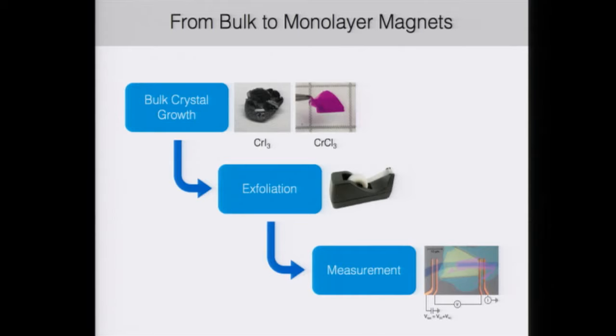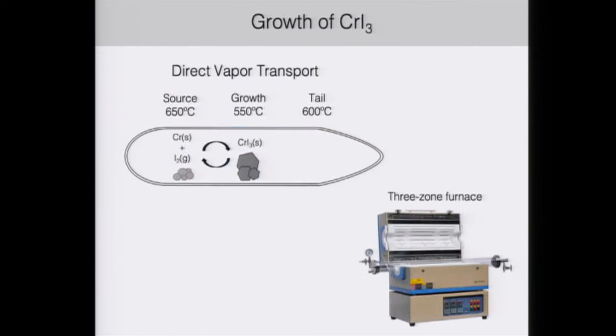So in our lab at MIT, we like to study what happens to crystals as we take them down to the ultrathin limit. So we begin with bulk crystal growth of chromium triiodide and chromium trichloride. We then can use Scotch tape to mechanically exfoliate them down to the monolayer or few layer limit. And then once we have identified these crystals, we can then fabricate devices and measure them in a variety of different ways. So I'm going to begin with this discussion on chromium triiodide.